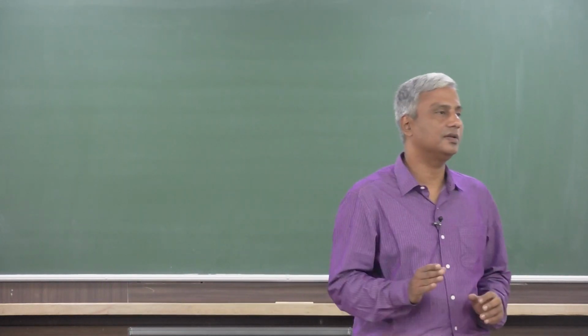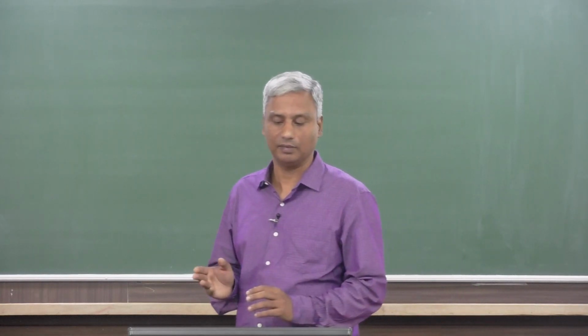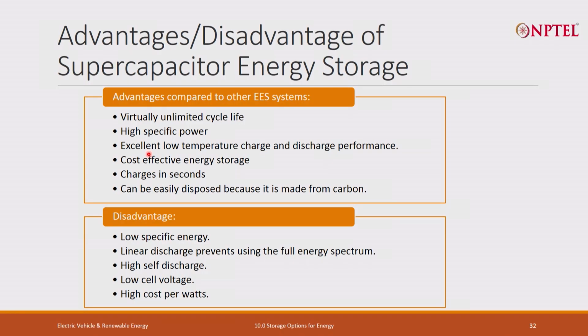Linear discharge: as it keeps discharging, the voltage keeps falling, so you cannot utilize the full energy spectrum. High self discharge is another problem. The cell voltage is very low, around 2 volts, that is another issue. Presently it has a high cost per watt, and that is what is preventing it from being utilized commercially at a high rate. Mainly two reasons: very low specific energy density, and the high cost per watt. These two reasons dominantly make it unusable at larger scale as of now.